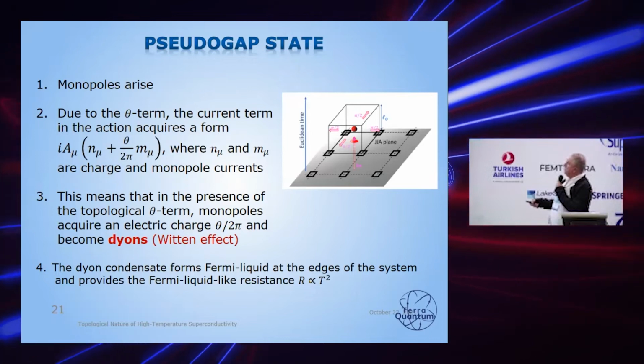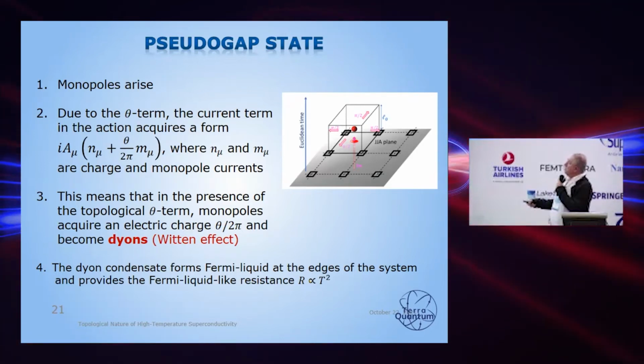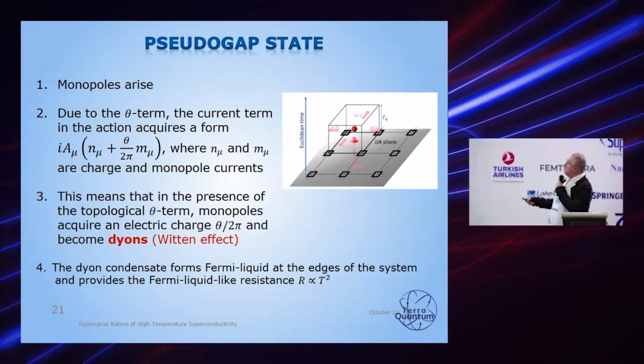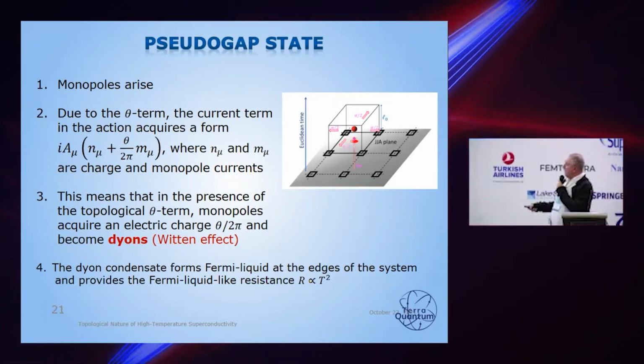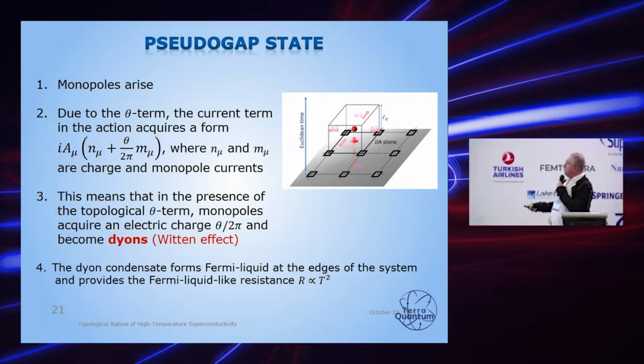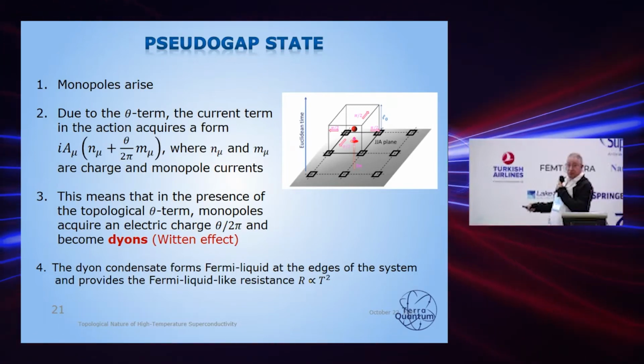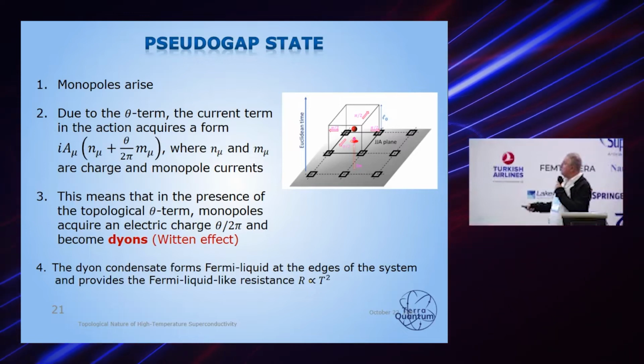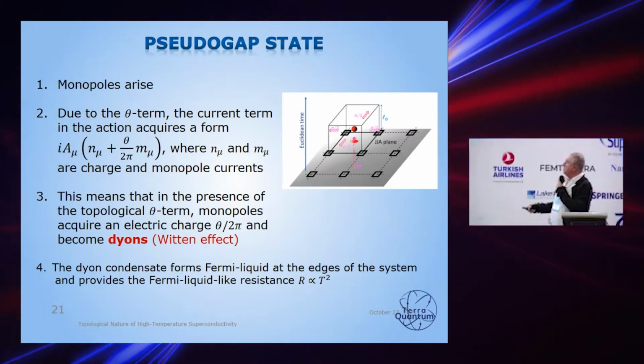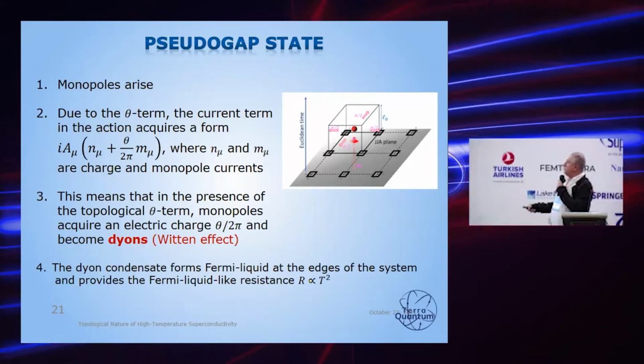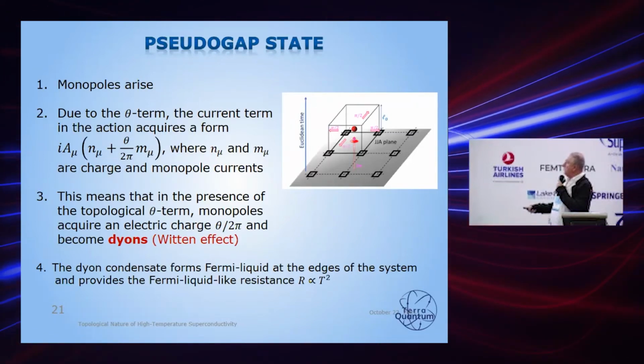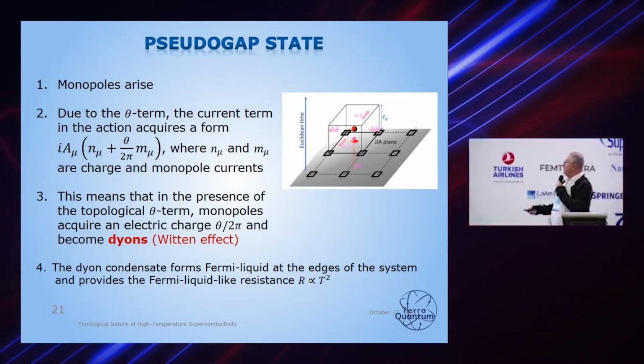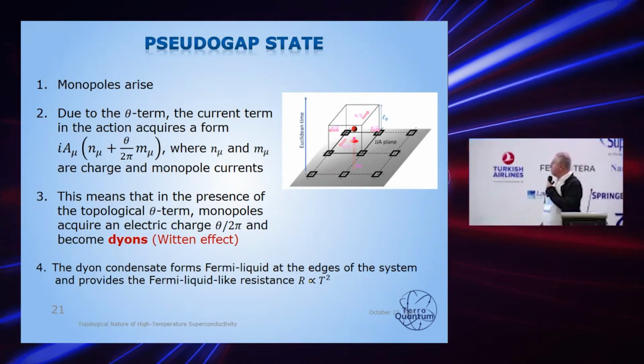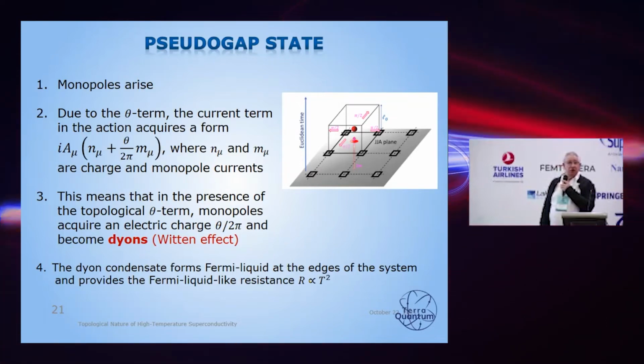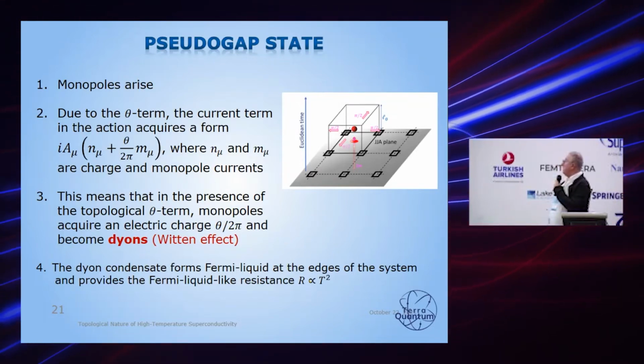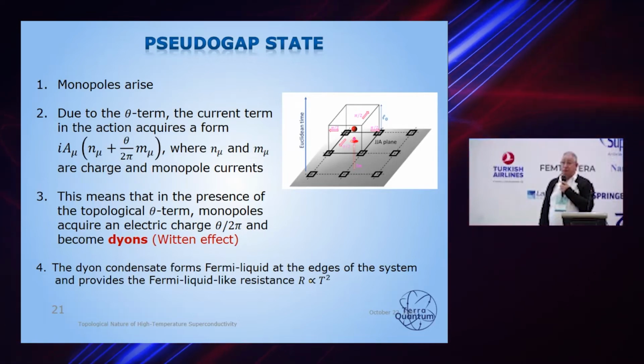And this is the form which the current assumes due to this theta term. And then again, I remind you that in the presence of this topological theta term, responsible for the magnetoelectric effect observed in the experiment, we have dyons which acquire both electric charge and magnetic charge. And this is a very well-known effect. It's called the Witten effect. And then we immediately understand where this T-square behavior appears from.